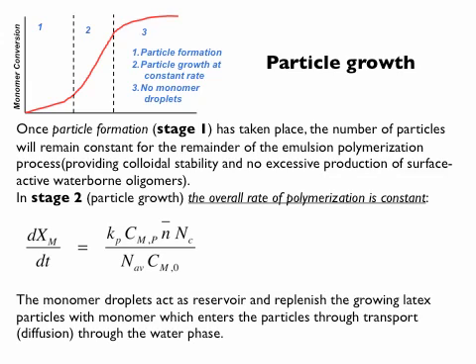In phase two, the rate of polymerization — the first derivative of the graph of monomer conversion versus time — is constant, giving a straight line, which is a bit strange. The overall rate of polymerization, predominantly happening in the particles, means that dx/dt is a function of several things. From polymer chemistry kinetics, you know the rate of propagation is responsible for the overall rate of polymerization, since the majority of monomer gets consumed during propagation: it's kp times monomer concentration times radical concentration.